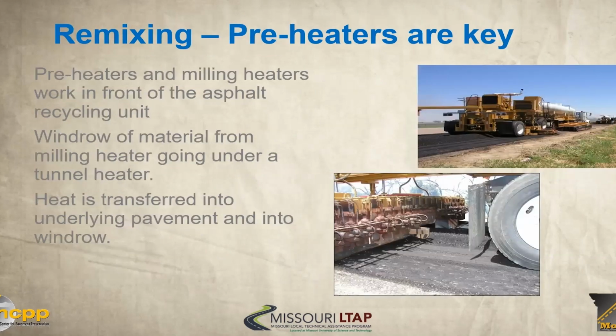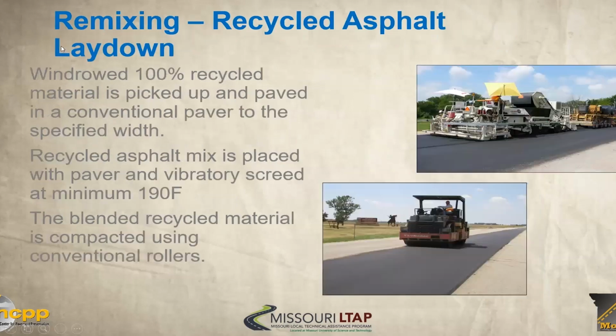As with any of these, the preheaters are key. That's why you saw that slide that showed a handful of preheaters in front. Here's the windrow you can see. You windrow this material from under the tunnel heater, and the heat is transferred into the underlying pavement and into the windrow. This is a very effective way to do it. The nice thing is that windrowed material, 100% of it is recycled material, and it's picked up and paved with that conventional paver. Then the recycled asphalt is placed with the paver, and you've got a blended recycled material that's compacted with conventional rollers.